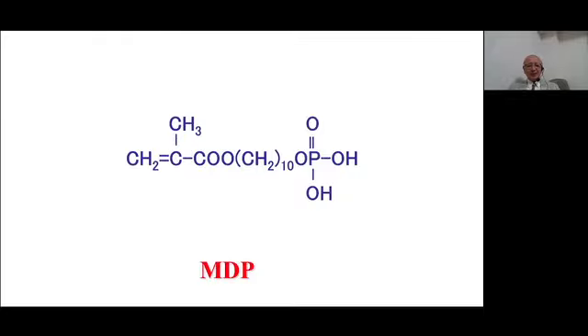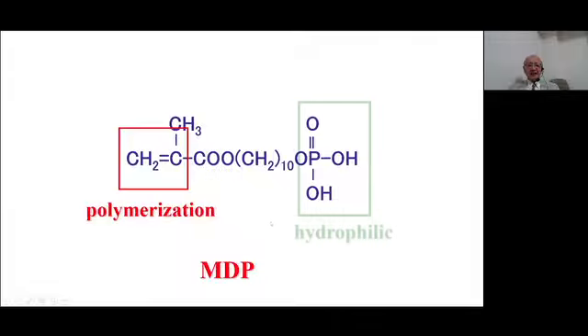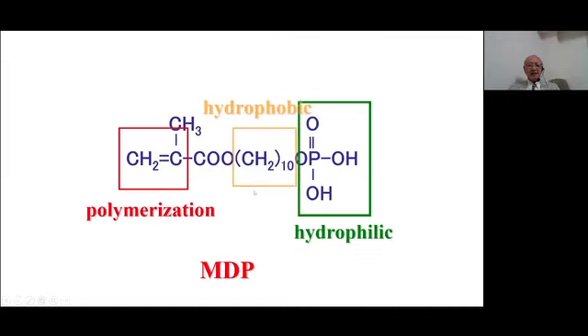The key monomer is MDP. MDP is shown here. This is the carbon double bond for the polymerization, and this is the phosphoric part for the bonding. This is the hydrophilic part, very important for bonding. And also this 10 alkyl chain is necessary to make this monomer hydrophobic, for durability of the bond.